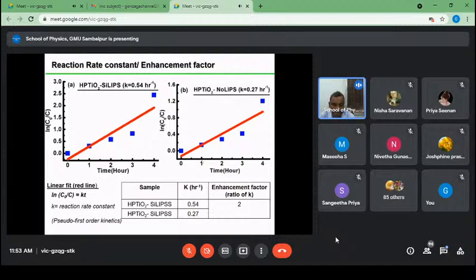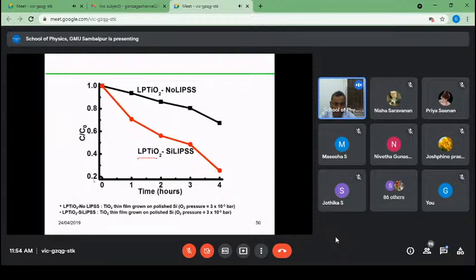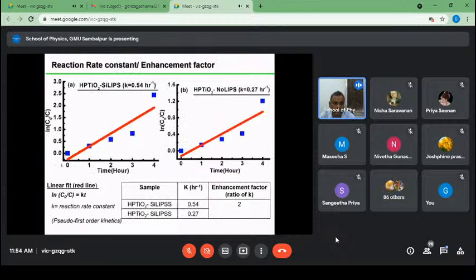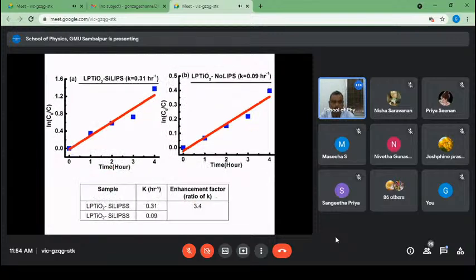And we have gone for some analysis. These are the standard analyses to find out the reaction rate constant, how fast the sample can decompose. Then we have found out the ratio. Generally, if you take C by C0 and take ln C0 by C, and plot time versus ln C0 by C, then it will give a slope, and you can do a curve fitting. This is called pseudo first order fitting. You can go for second order fitting also, but mostly the reactions are first order. And I found that the enhancement of the reaction rate can be 2 times using SiLIPSS. Similarly, in the low pressure case also we can enhance it.